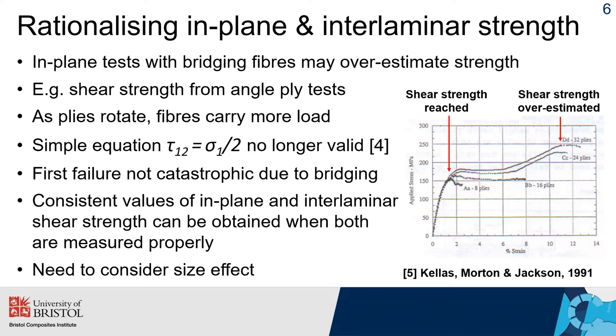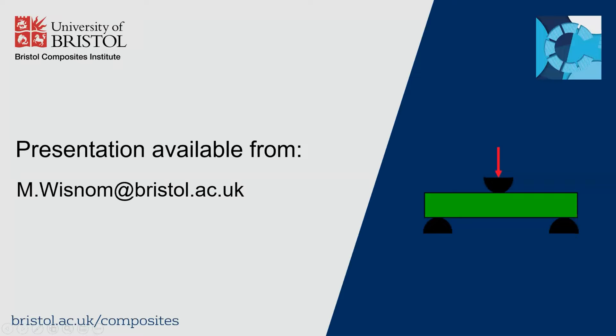If you look at strength data, you will often see differences between in-plane and interlaminar values. For the short beam shear test, the shear strength values depend on having the correct stress distribution. The standard linear equation assumes a parabolic shear distribution, but nonlinearity of the material changes the maximum stress — it becomes much flatter in the middle — so the interlaminar shear strength from this test is typically overestimated by around 15%. For the ±45 test, when you have large shear deformations, fiber rotation causes the fibers to carry larger tensile stress, so the ultimate strength is not valid for shear. You can get consistent in-plane and interlaminar shear values if properties are measured carefully, but you must consider the size effect and also the laminate-level effects related to number of plies, ply thickness, and edge stresses. Thank you very much.